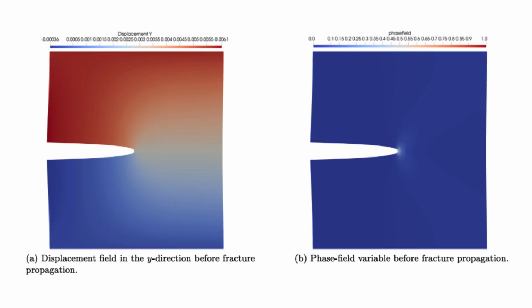So the big takeaway here, the so what, is massive. That simple, stable AM algorithm, while great for learning and ensuring it works, becomes cripplingly inefficient right at the crucial moment. Exactly. If you tried to use this exact code for a large, complex engineering problem, say a whole airplane wing or a bridge component, that spike to 405 iterations would mean hours, maybe days of extra computer time just grinding through the moments of failure initiation. It highlights the classic trade-off, doesn't it? Implementation simplicity versus computational performance. The AM algorithm works, it's robust, it's relatively easy to code, but it crawls when the physics gets intense.